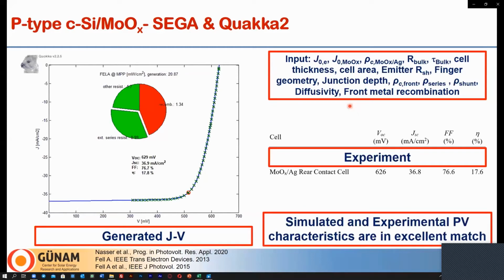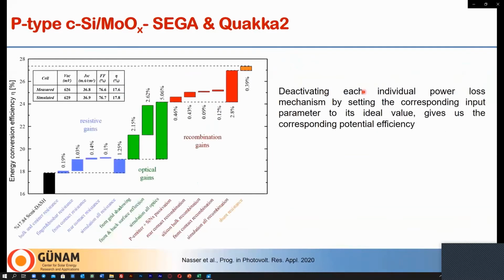And both fabricated and simulated IV characteristic of the cell agree well. So this is the experimental result, and this is the simulation result. There are, of course, small deviations, but these small deviations still can assure that the measured values are correct because they were able to generate the experimental data. So this is SunSolve analysis of our fabricated P-type solar cell with molybdenum oxide silver rear contact.